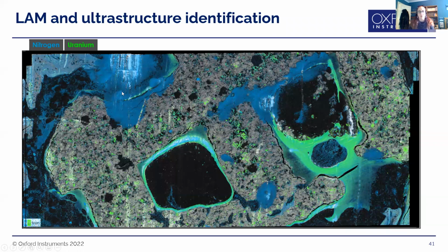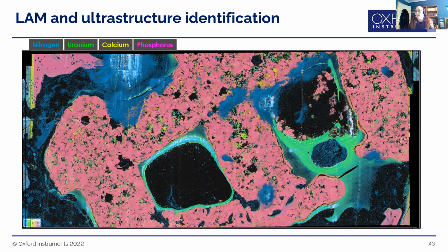Where it doesn't, it's likely that we're getting an accumulation of polypeptides that would occur around the edges in the extracellular matrix around the implant. Quite interestingly, we've got a rather strong uranyl acetate signal here. Now, uranyl acetate is also known to bind to collagen particularly well, so it's entirely possible we've got a collagen deposition occurring in these areas, possibly where we've got new bone growth. So we've got lots of different areas within this sample that we can now identify. In here we have the calcium map, and here we have the phosphorus map. And again, you can really see then the difference between the implant and the cellular material within it.